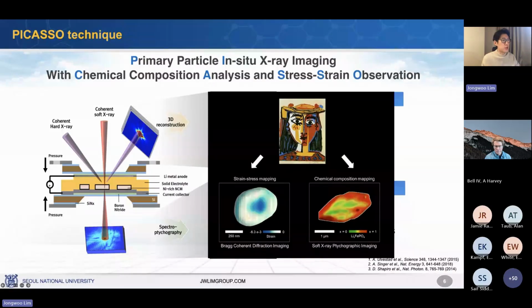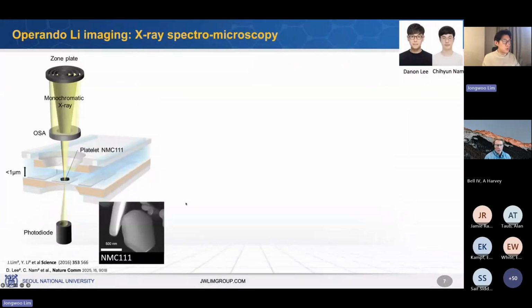So first things first, we use NMC 111. NMC 111 is a well-known solid solution material, and it's also a well-known two-dimensional lithium-ion battery particle like this one. It looks like a platelet particle. So we place this particle and shine X-ray light on it, and we also make sure these particles are cycled within micro-sized, customized, fabricated battery cells.